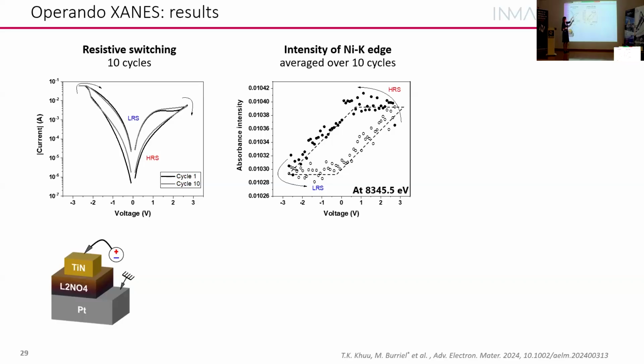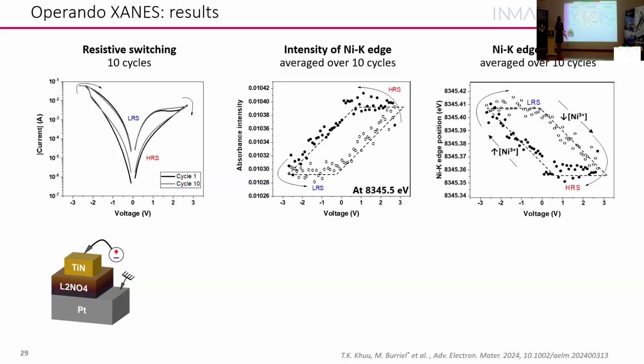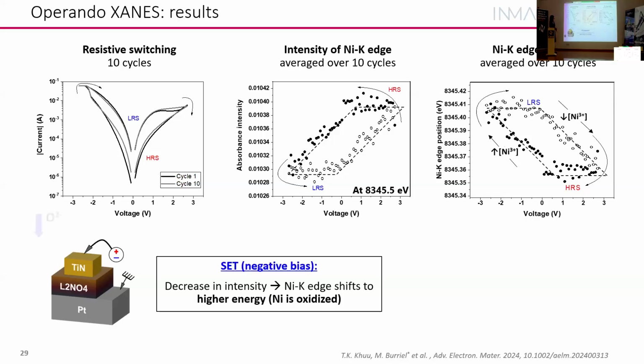the absorption intensity. So here we're in the high resistance state, and then we see a change, and here we're in the low resistance state. So the intensity really increased and decreased, and we can directly estimate the nickel oxidation state from the nickel position. And at the end, we can relate it to what's happening in our sample.